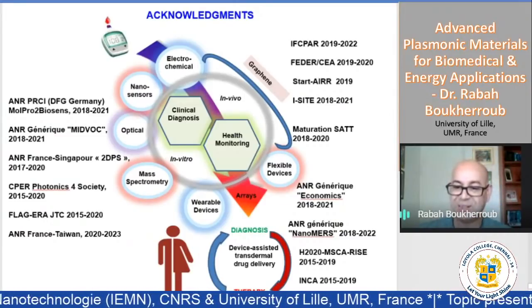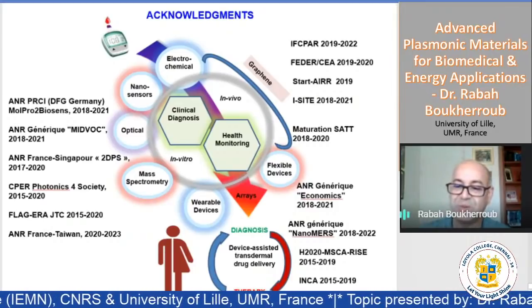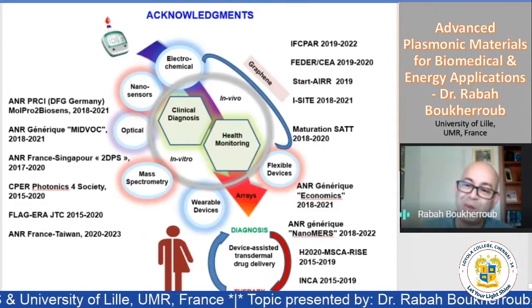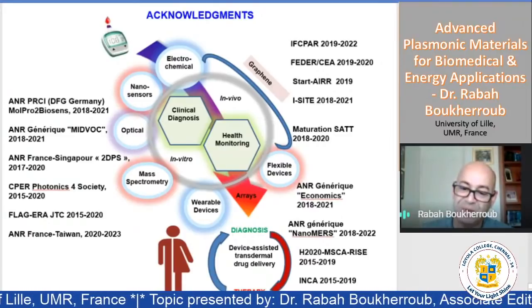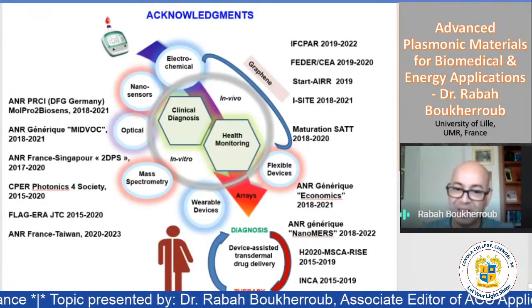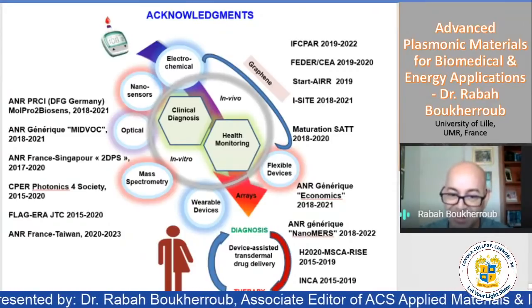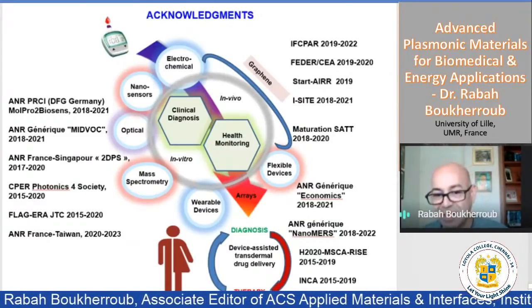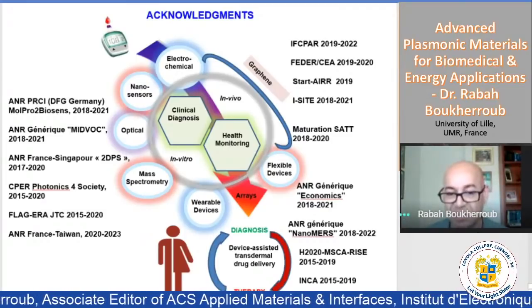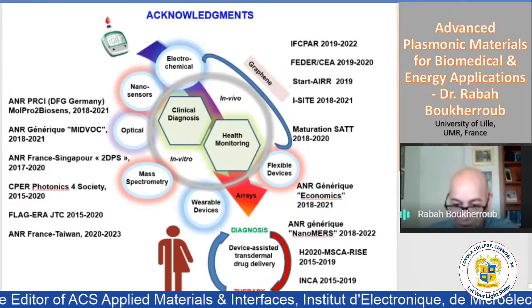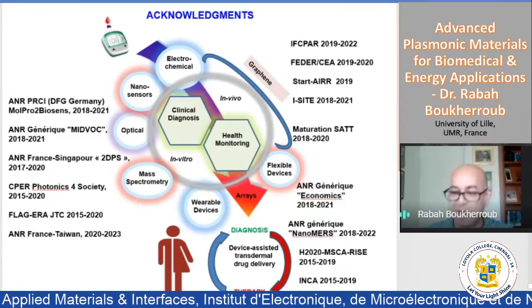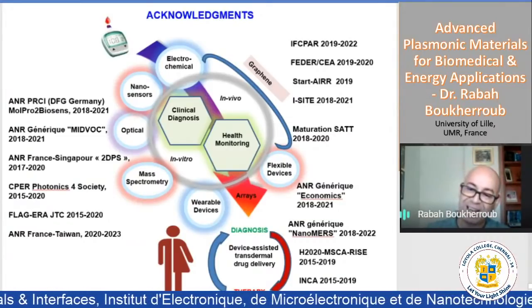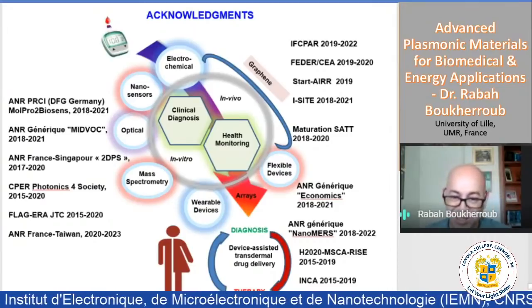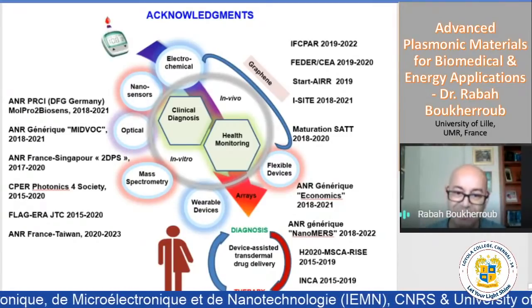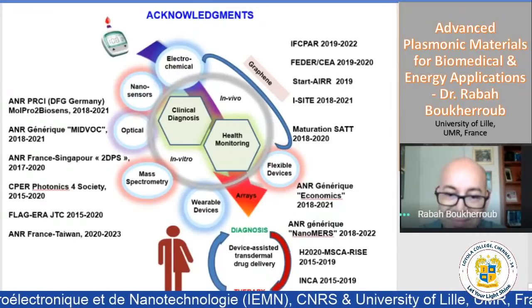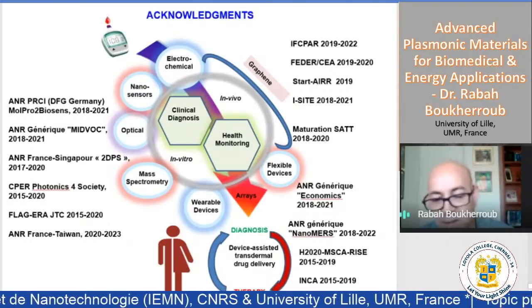When it stands perpendicular to the surface, it acts like a knife. If you put a cell or a bacteria, no matter what type of cell, the graphene goes in between, goes into the membrane and can open up channels, and then you empty the content of the cell and you kill the cell. People call that antibacterial, but in reality it's not antibacterial, it's just a mechanical effect. If you have flat graphene, it's biocompatible. But if it stands slightly like a knife, it could potentially interact with the membrane, open it up and kill. So graphene itself is biocompatible, yes.